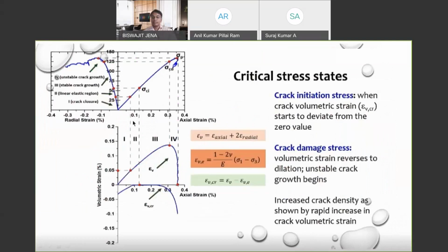Now, slightly more different structural aspect to think about when you design this mix. What I have shown in this picture on the left top is the stress strain curve, but marking significant points on the stress strain curve based on the strain relationship. And the bottom curve is the axial strain versus volumetric strain, so the response of axial versus volumetric strain. Volumetric strain is nothing but the axial strain plus twice the radial strain, and the volumetric strain you can get from a simple transformation using Poisson's ratio and the principal stresses, sigma 1 and sigma 3. The volumetric crack strain is volumetric strain minus elastic strain. The elastic strain up to 50% of peak is a random definition. So if you look at this, there are some very interesting points.